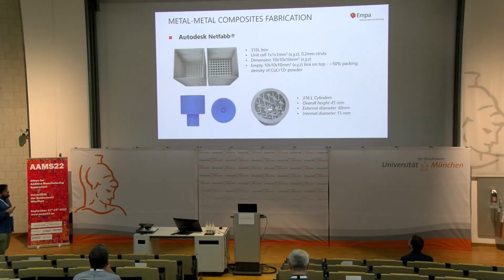At first, we used the commercial software Netfabb from Autodesk, and we designed two principal geometries. The upper one is a lattice with an overall height of 2 centimeters, which is split into two parts. The lower part has been incorporated with some struts or a grid structure where we plan to infiltrate the powder and create the composite material, and we have an upper part which is empty. The reason is that at the beginning of the process, we want to have more powder because we expect a packing density of the powder around 50% of the bulk material.